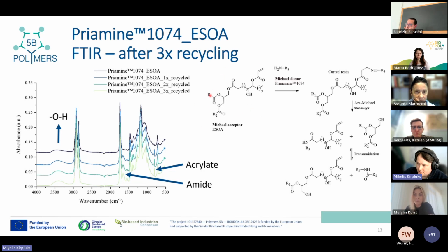It has a triglyceride structure with a glycerol ester backbone in the middle. After recycling the material, when the aza exchange occurs, there is a possibility that the released amine can react with this glycerol backbone, releasing the OH group, which afterwards can no longer cross-link the network. The cross-link density of our network decreases, and basically in the end, from an elastomer we obtain just a goo, which cannot be classified as a material anymore. So at the moment, what we're working on is to mitigate it.